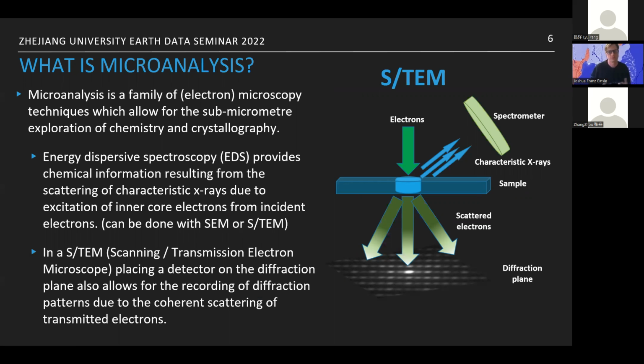So most of the measurements today are going to be done in a scanning/transmission electron microscope. I can either run it as a scanning transmission electron microscope or just in pure transmission mode. Regardless, the data we're going to look at resolves on two different ways of interacting with the sample. We shoot high energy electrons at the sample. These interact with the sample and they can emit characteristic X-rays in a spectroscopic technique known as energy dispersive spectroscopy.